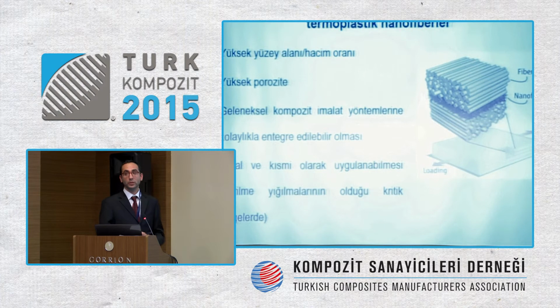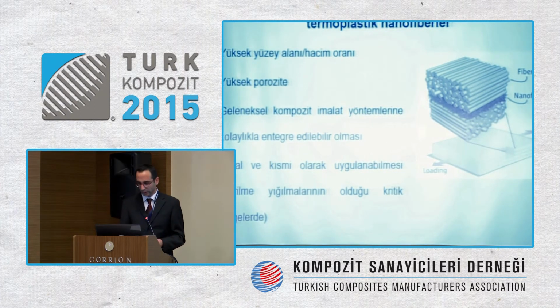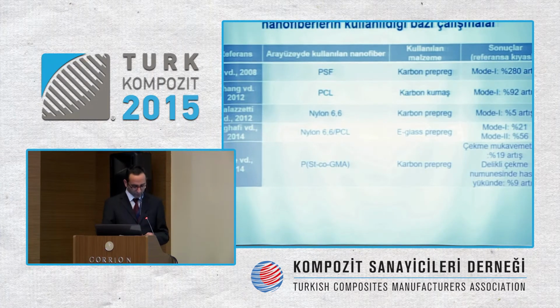And in the interlayer interface, we looked into the usage of electrospun thermoplastic nanofibers. Why? Because they have a high volume ratio and surface area, and it increases the interaction with epoxy. And they have high porosity, and it facilitates the flow of the epoxy. And this can be easily integrated into conventional composite manufacturing methodologies. And rather than being applied to the whole piece, it may be locally or partially applied.